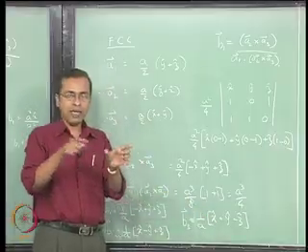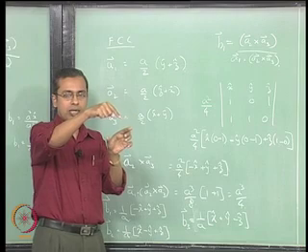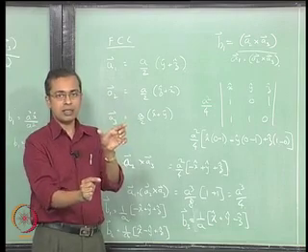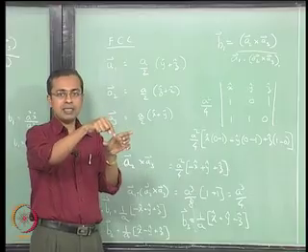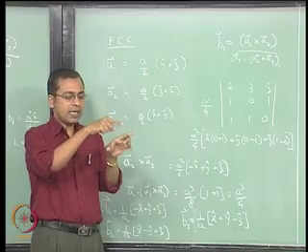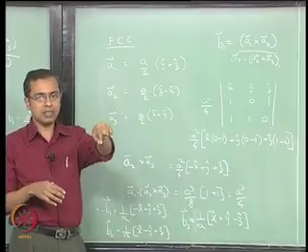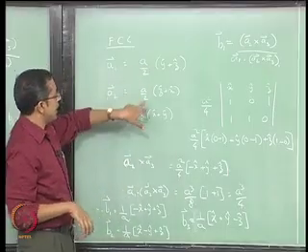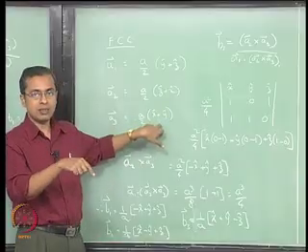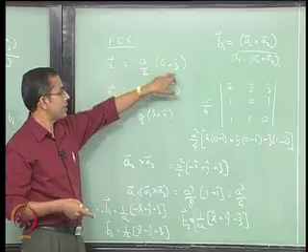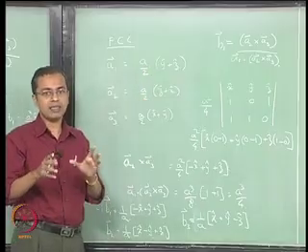If it's x plus y, you are going along x direction plus y direction, and then minus z, so you are going down, so you are getting to one body center in that location. If you went only x plus y, you would get to the face center, right, x plus y with some constant. So in fact a by 2 x plus y would get us to the face center, a by 2 z plus x gets us to the next face center, a by 2 y plus z gets us to a third face center. So these are face centers, right.